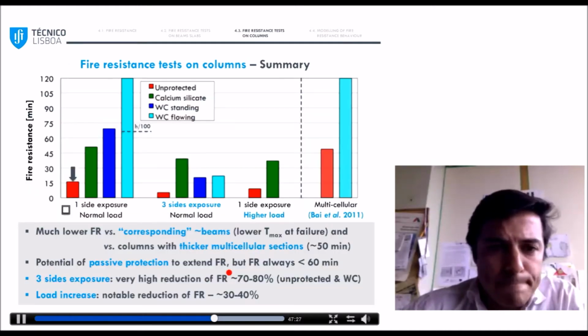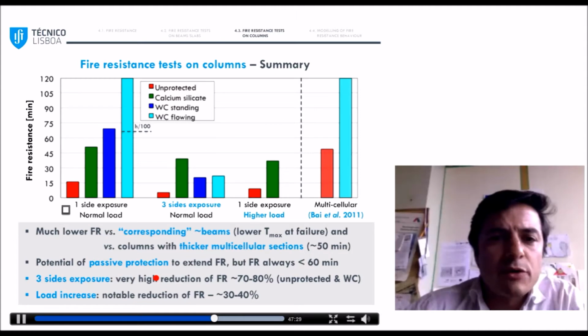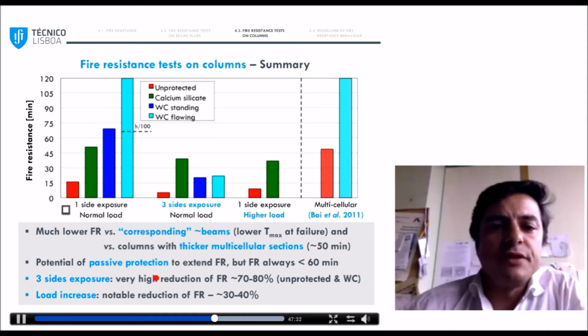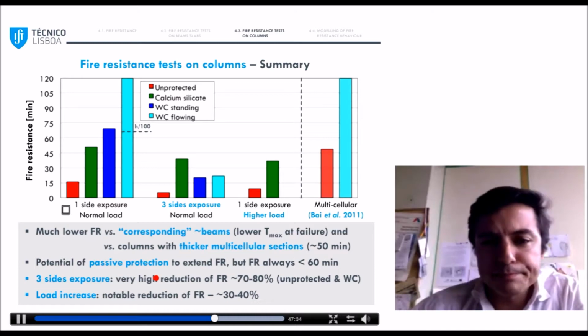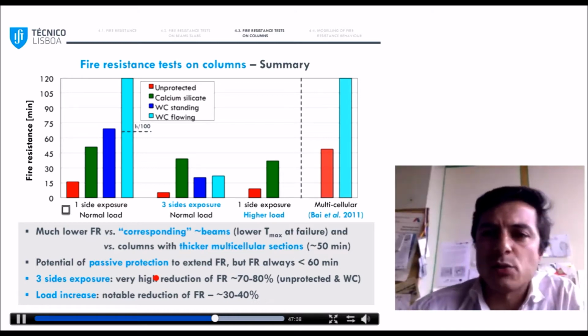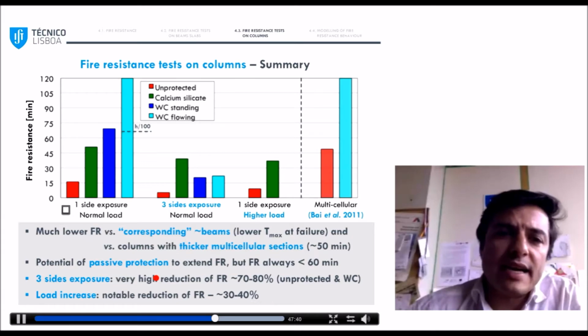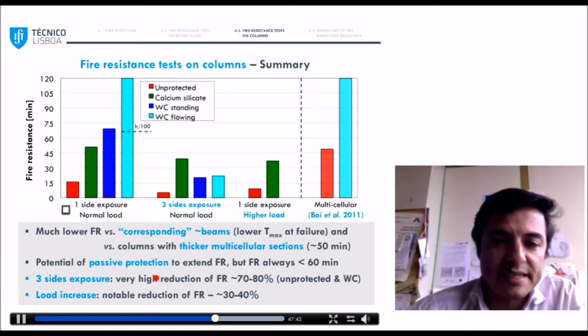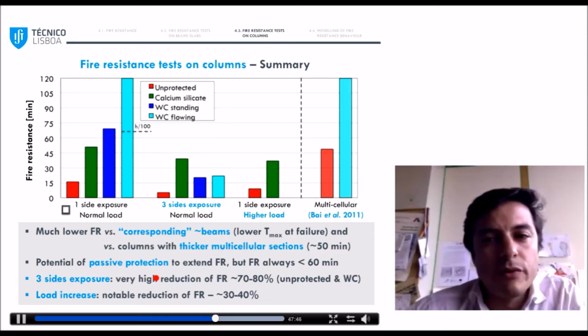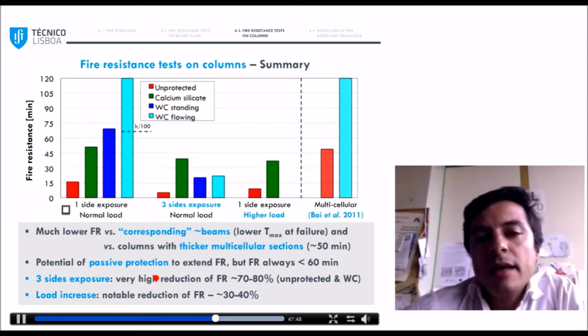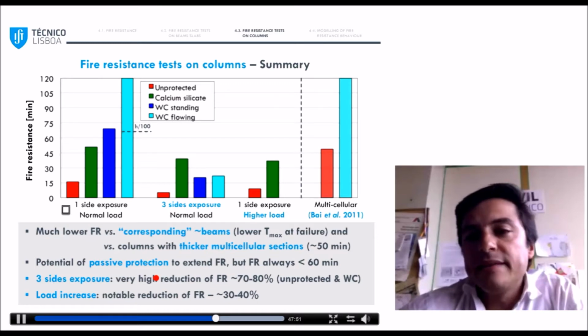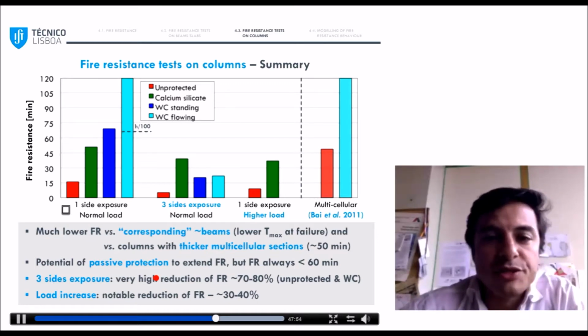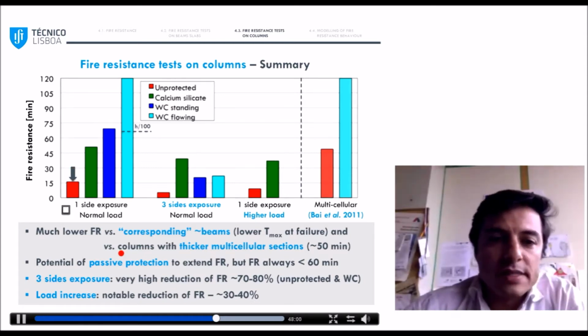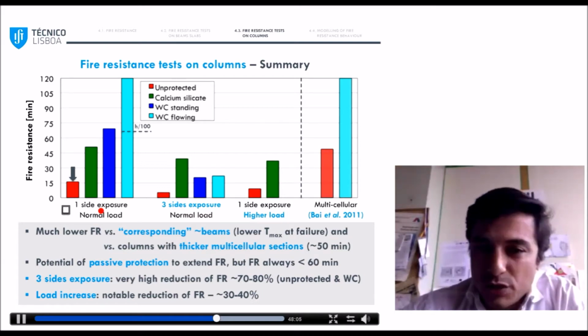So here you can see a summary of the fire resistance of the different columns tested in this study, and also a comparison with results obtained elsewhere. First, I would highlight the much lower fire resistance of the columns compared to equivalent beams, if this comparison can be made. This is basically explained by the lower residual strength of the material in compression. For the unprotected column under one side exposure, so this one, the resistance now was only 15 minutes, which is very low.